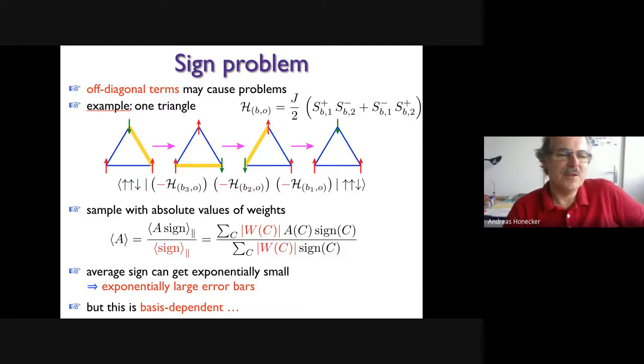Let me give you an example and go back to a single triangle, where I'm assuming an initial configuration of two spins up at the bottom and a spin down at the top. The off-diagonal operator here is the pair flip of two spins across a bond. You can flip spins along one edge, flip them along a second edge, flip them along a third edge, and you're back to the initial configuration. Meaning there is a diagonal matrix element that contains three products of minus this thing, and that is definitely negative. So if you have a triangle in your system, these off-diagonal terms give you negative weights in that basis. Well, the standard way out is to close your eyes and take the absolute value of these matrix elements and sample with respect to the absolute values.